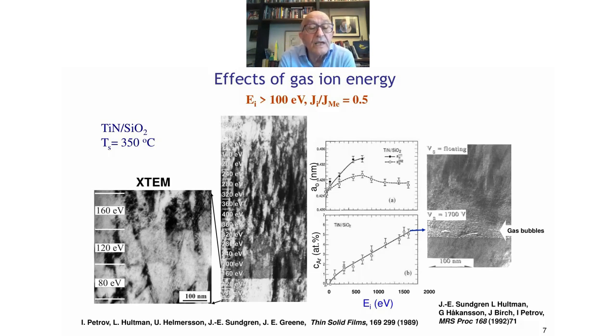If you look at the high amplification to the left, at the bottom we see porous grain boundaries, and at about 120 volts, these pores close, but we also see these speckles inside the grains, and this is because ions penetrate into the lattice. They cause collision cascades, which cause densification, but also there's trapped residual damage and trapped argon. And at 160, this is very much pronounced, as you can see in the right picture. And eventually at high voltages, we get renucleation. So that's the price we pay for densification by ion bombardment.